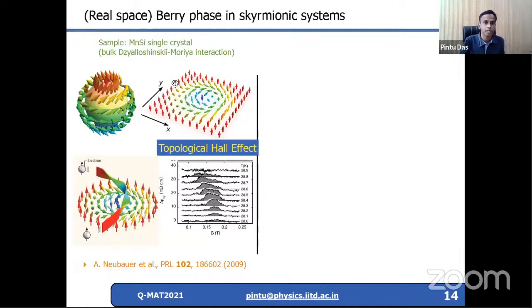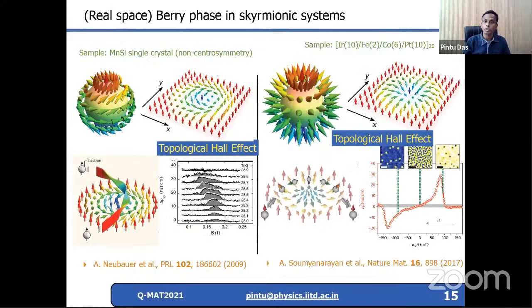which I show here for manganese silicide, where the skyrmion is stabilized in a small temperature regime between 27 to 29 Kelvin. So you see that as the temperature goes up, this topological Hall effect goes away. Similar features have been observed for room temperature skyrmions also, as I said, for the multilayer systems where there is an interfacial Dzyaloshinskii-Moriya interaction. This group has shown in iridium iron cobalt systems and cobalt platinum systems this topological Hall effect feature that people have reported. And these topological Hall effects are related to the skyrmion density, as they have shown.